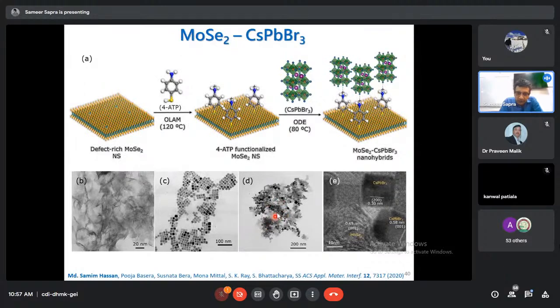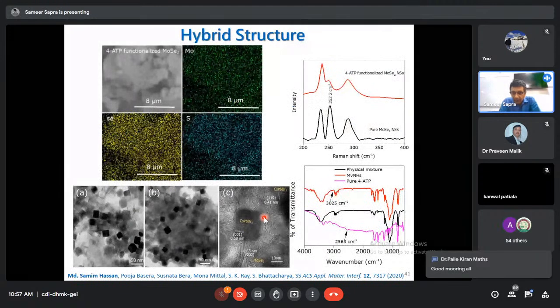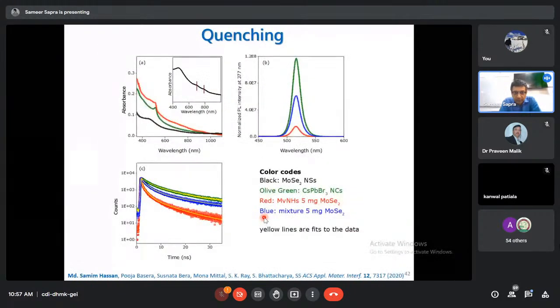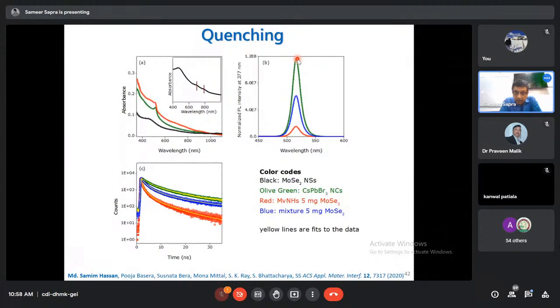By the way, all these heterostructures are washed at least 5 times to ensure that no free particles are there. Okay, so all these heterostructures, you can also see, again, lots of evidence, let's not worry about it. You can also see that cesium lead bromide has a very high fluorescence quantum efficiency, roughly at about 515 nanometers, which drops drastically when you make these heterostructures, the linked material, okay?